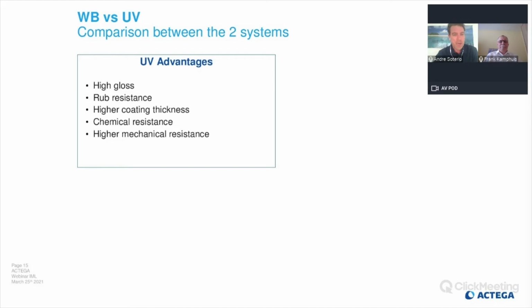First of all, in UV coatings, you have a very big advantage, which is the high gloss. It's very difficult to match the high gloss that you get with UV with a water-based coating. Even if you use high gloss water-based coatings, you get a big difference between on top of the ink and on top of the film itself, with no ink underneath. The second main advantage of UV coatings is that the rub resistance is far better than water-based coatings. Then we have higher coating thickness, as Frank said, since there is no evaporation of the water. So what you apply, you can get. It remains on top of the film. Depending on the application and the level of resistance you need, you can apply a very high coating thickness.